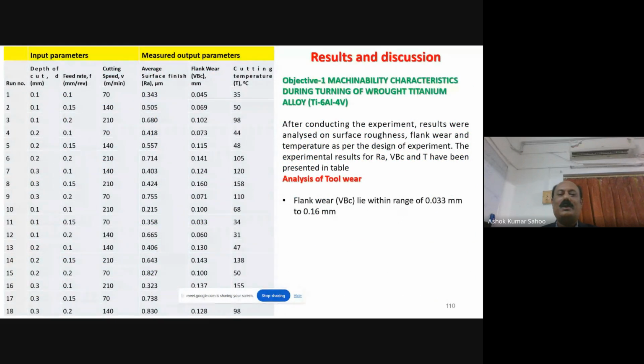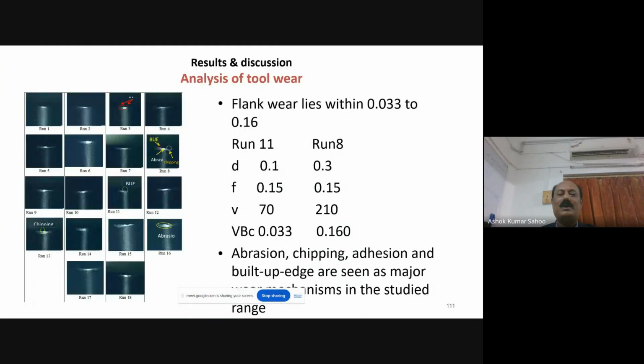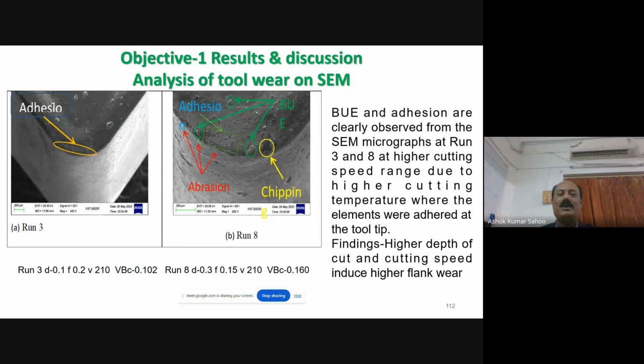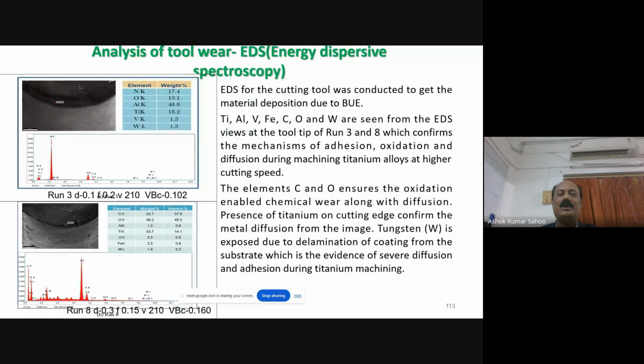These are the experimental results and findings for objective 1 for wrought alloy, where flank wear lies between 0.033 mm to 0.16 mm, where the acceptable limit of flank wear that we have taken for finishing machining operation as per ISO standards is 0.2 mm, and the surface quality acceptance limit we have taken as 1.6 micron, comparable to the surface grinding operation as per ISO standard also. A lot of adhesion, built-up edge formation, chipping, and abrasion are clearly observed in the EDS analysis of the wrought titanium alloy.